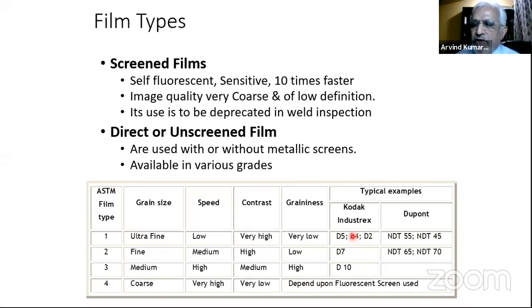If you have to do gamma radiography of say 3 mm, 4 mm, 5 mm stainless steel or cupronickel or aluminum, things like that, then you have to go for D4 films with selenium 75 source. And if you still don't get the required sensitivity, you have no choice but to go for X-ray.